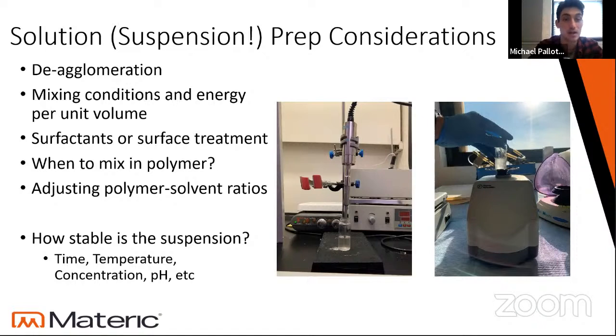The first one is deagglomeration. We'll find that nanoparticles, if they're tacky enough, will stick together, and that will end up affecting the uniformity of your final product. So we'll use methods like horn sonication and vortex mixing in order to break up and make a uniform solution such that when we spin, nanoparticles and additives are spread uniformly throughout our final nanofiber mat.